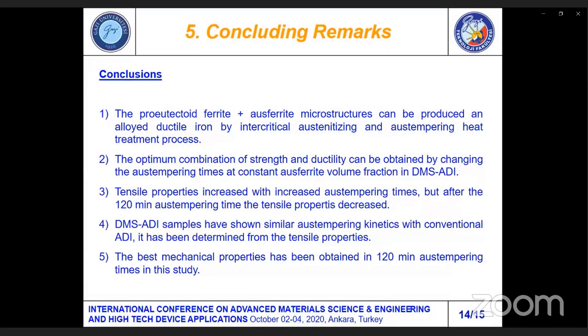Tensile properties increased with increased austempering times, but after the 120 minutes austempering time, the tensile properties decreased. Dual matrix structure austempered ductile iron samples have shown similar austempering kinetics with conventional austempered ductile iron. It has been determined from the tensile properties. The best mechanical properties have been obtained in 120 minutes austempering time in the study.